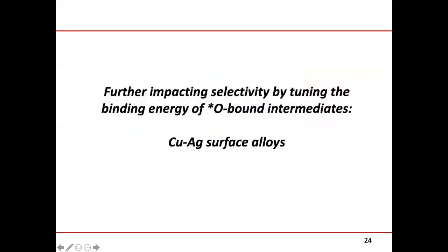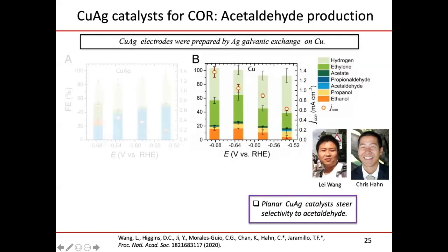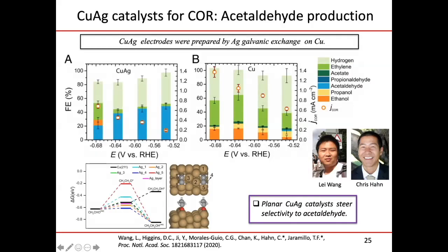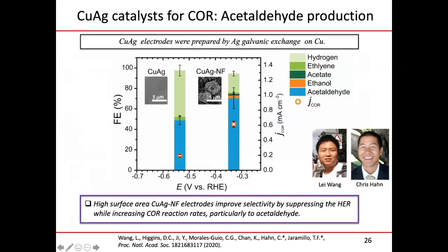And then we took it one step further, and we started making copper-silver surface alloys, for the reason of really trying to change the properties of binding of intermediates on the surface. And so looking at the colors of these diagrams, we're looking as a function of voltage. These are bar charts that give you a sense of the selectivity of the different products being made. This is pure copper. This is just dosing a little bit of silver on the surface. And you can see just by eye, it's striking. You're getting a very different set of product distribution, really focused on acetaldehyde. And we have DFT calculations that support why the difference in chemistry can be so great just by doping the surface with just a little bit of silver.